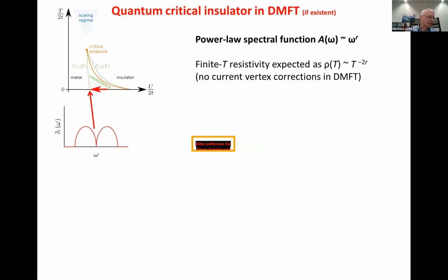Now, if this actually happens, the spectral function would have a power law. From this power law, assuming an exponent R for this spectral function as a function of frequency, one can immediately deduce that the resistivity would diverge as t to the minus 2R, because in DMFT there are no vertex corrections. So this would be an insulating state with divergent resistivity, if you cool it down.